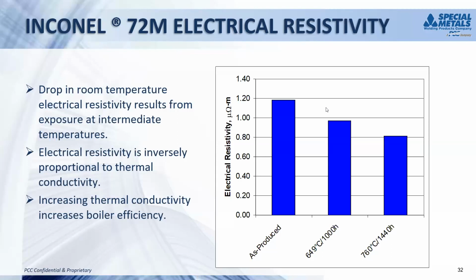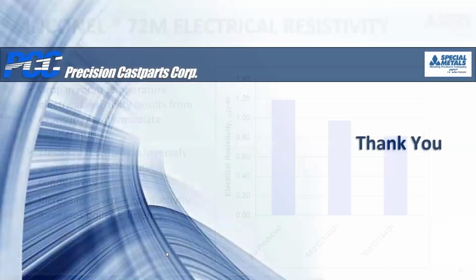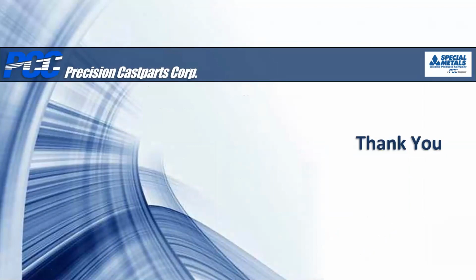And why is that important? As you can see on the second bullet point, electrical resistivity is inversely proportional to the thermal conductivity, which basically means the longer this alloy is in service, the better the heat transfer is in this alloy and the better the efficiency is of the power plant. So that was a very interesting nuance that popped up, but it was a very big advantage to some of these newer alloys as far as cladding, not just to protect the existing system, but to actually increase the efficiency of it. Thank you for your time. We'll be addressing questions at the end.